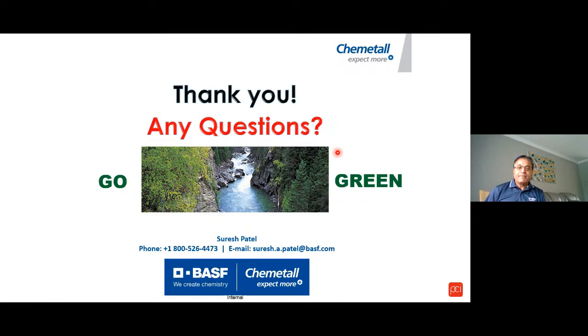All right. Cleaning before the pretreatment is already a challenge for the industry. Are there any plans to develop zirconium pretreatments that are more forgiving to less than optimally clean parts? That is always the case, and I'm sure many companies like us are looking into that. At this point in time, I would say the answer is no, because of the weaker acid, the hydrofluorozirconic acid, that's the primary component pretty much being used in any zirconium pretreatment. It does not do the heavier etching compared to the conventional one.